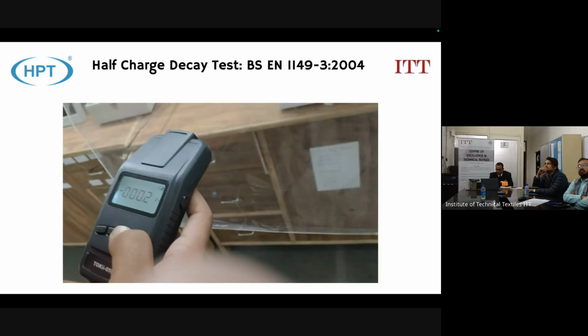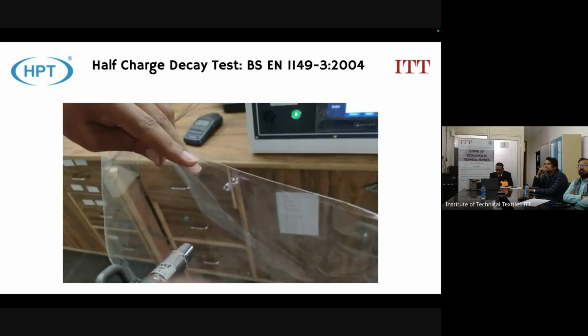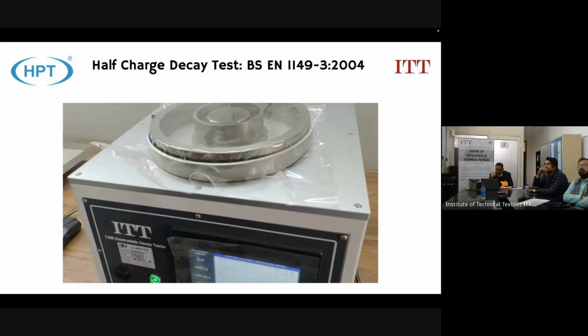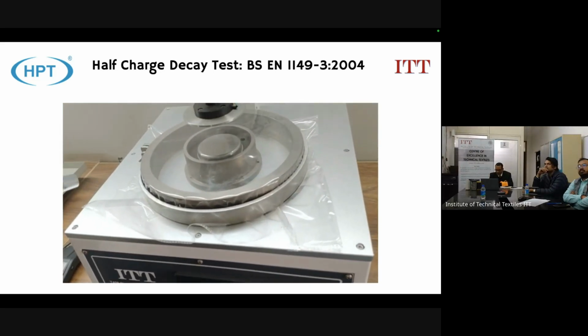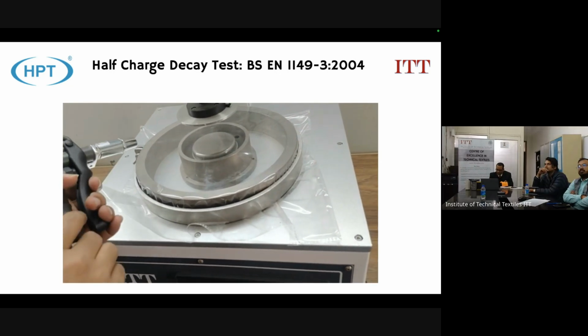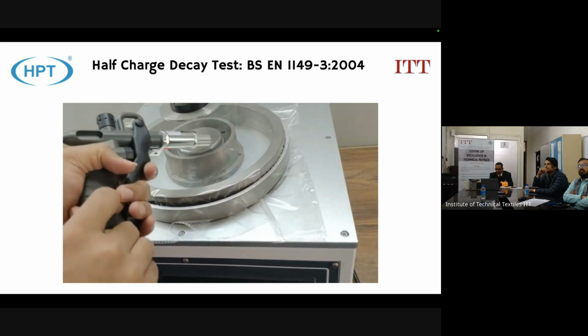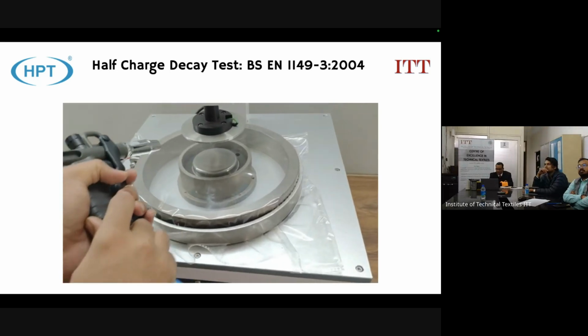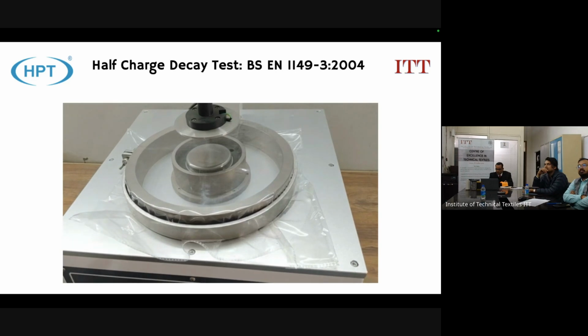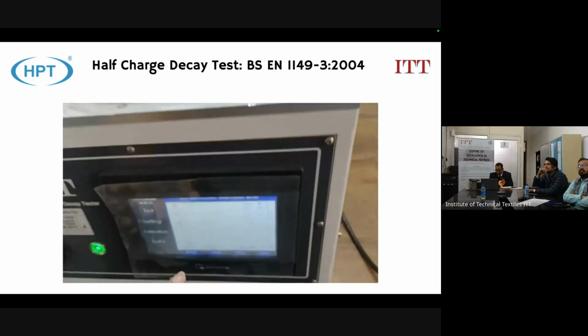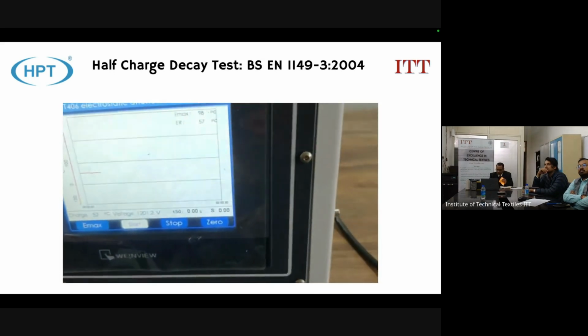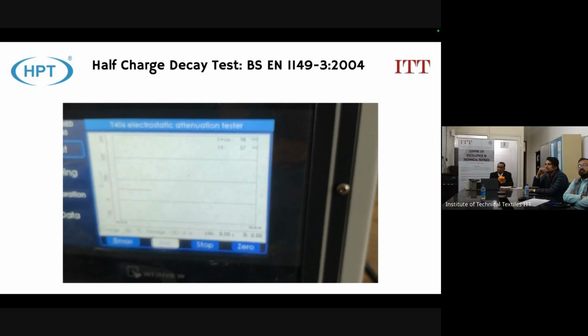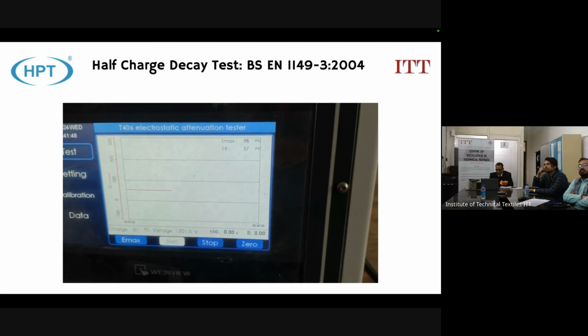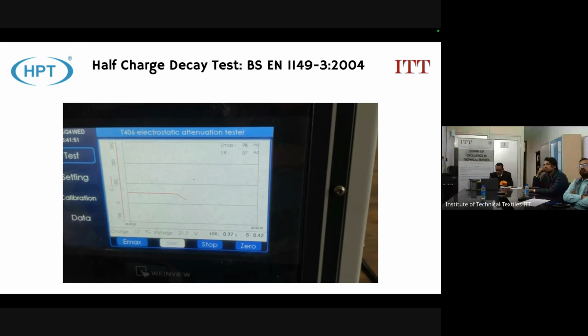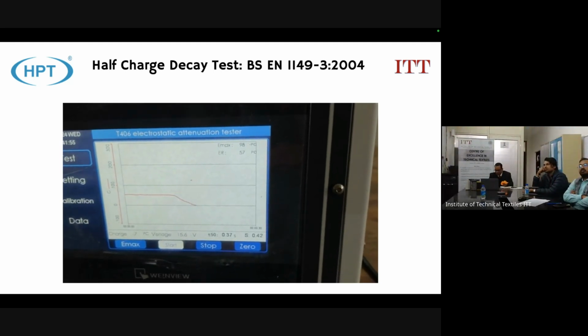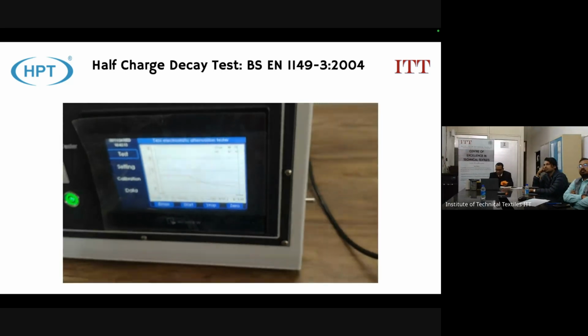At the bottom we have a voltage generator. Before we put the sample, we are checking the charges available. We have to make sure that we are using an ionized gun to remove all charges before testing. So initially the electric field was generated, and then we put the sample and again check the reduction in electric field. Like I said, RH is very important. The whole area RH should be 20% to get good consistent results, which can give you the same results as European labs or overseas labs. So we have the maximum electric field and then the reduction because of the polymer material.